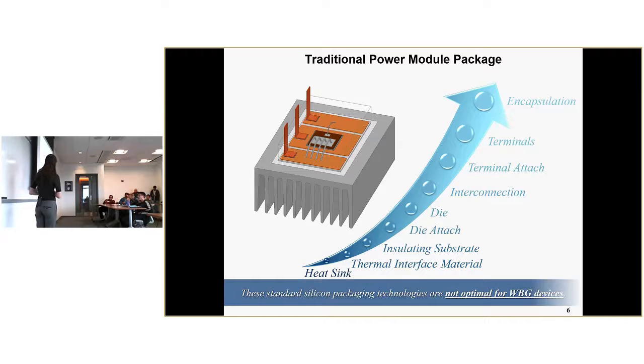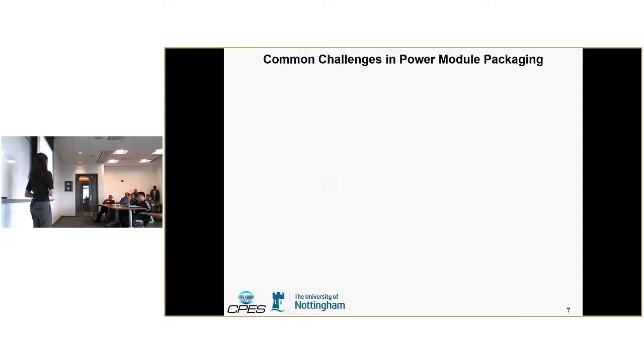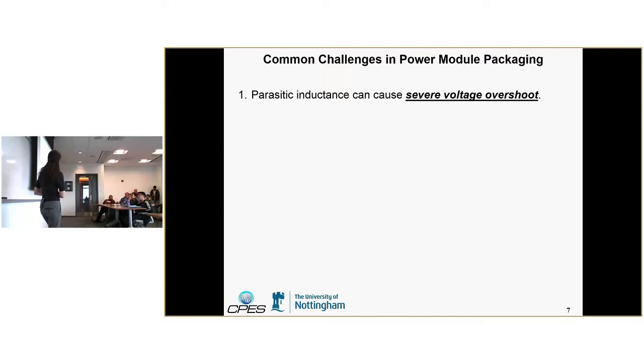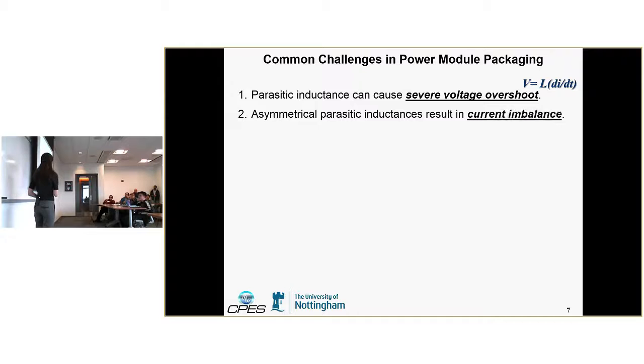These are standard packaging technologies that were developed for silicon. They work well for silicon for the most part. They also have some issues there, but they're especially not optimal for wide bandgap devices. Some of the challenges that are common in power module packaging are that parasitic inductance can cause significant voltage overshoot as well as ringing in your circuit. This is seen just from the equation, voltage equals inductance times your rate of change of current. Then asymmetrical parasitic inductance is also an issue.